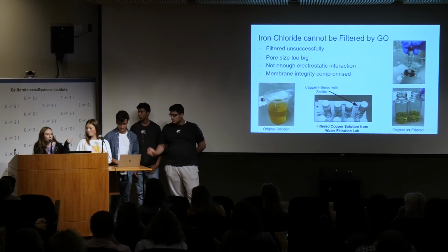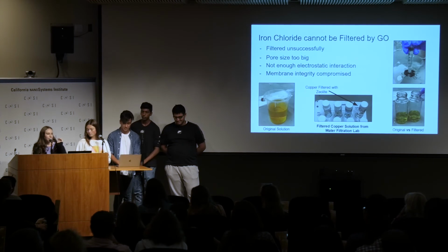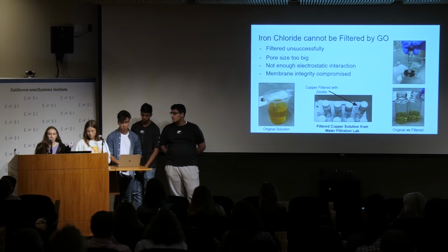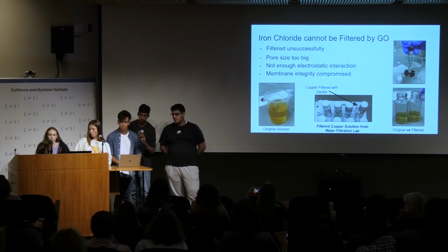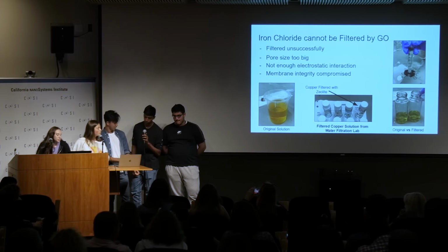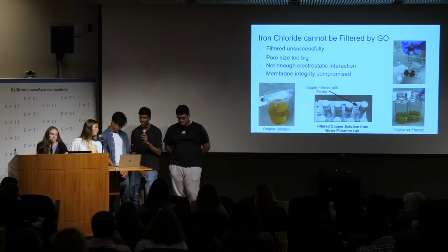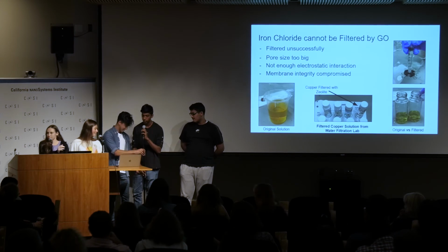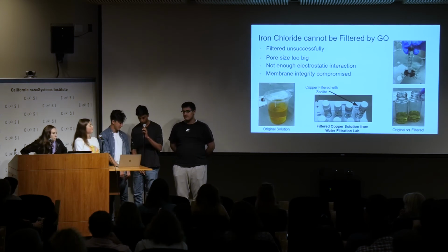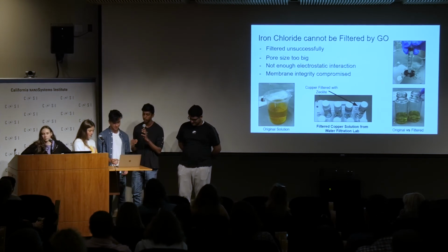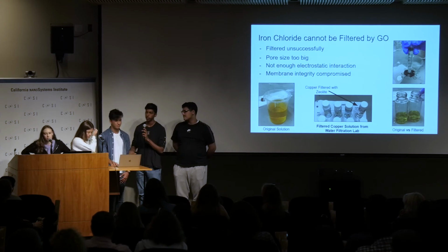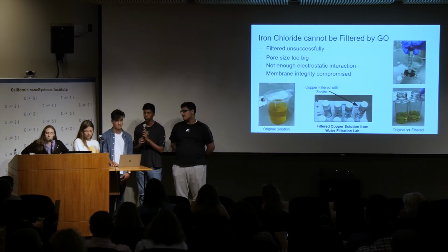Well, we originally were going to use the sonicator, which we had, and we listed that it didn't actually end up breaking it up enough, but it does break up the sheet so that it would create different size pores, and depending on how long you would actually use it for would depend on how big the pores got and how broken up the graphene oxide sheet would be. And another thing that affects the filtration is not just the pore size, but the number of layers, right? So graphene oxide is so thin that the layering is staggered, so that even if it gets through one layer of the pores, it'll still be caught in the next one. But we had such a thin layer and such a diluted concentration that it really didn't work as well with this solution. Thank you.